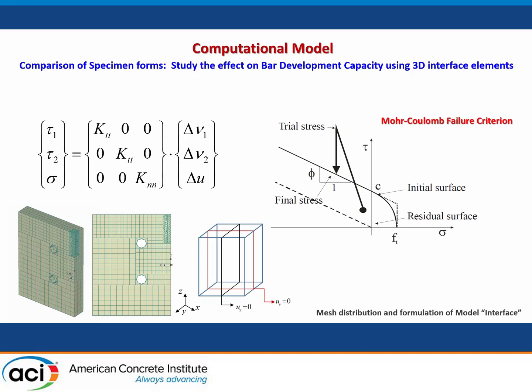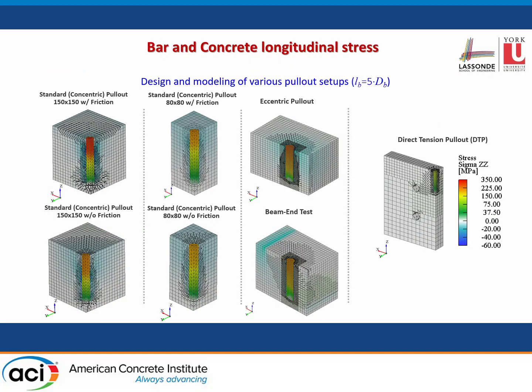And of course, wherever symmetry would allow, one quarter of the specimen would be modeled in order to ensure that we have optimal use of the computational power. So here, I hope this depicts easily for you the effect. I'll explain what you see. You see different types of specimens. On the top left, the standard pullout with friction at the top where it bears on the steel bar. At the bottom, you have the standard pullout with the Teflon pad so that friction is eliminated. Then next, you see the same friction and non-friction conditions for smaller size pullout cubes.